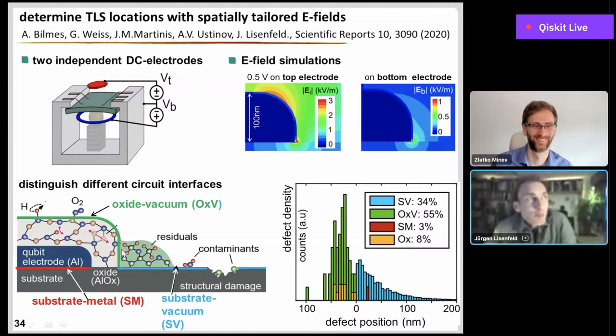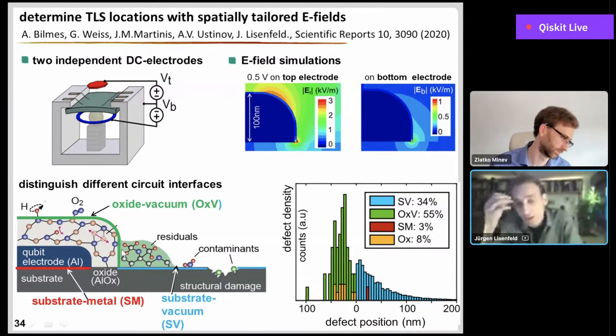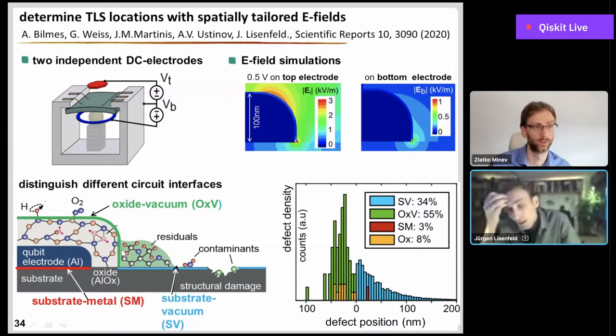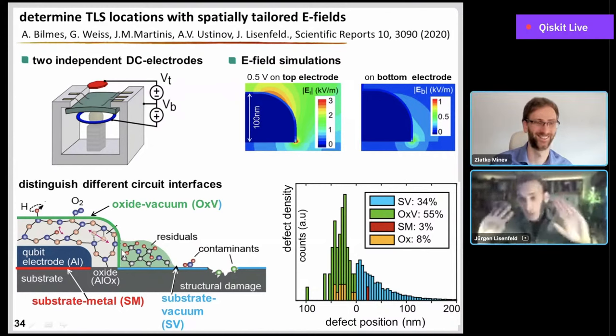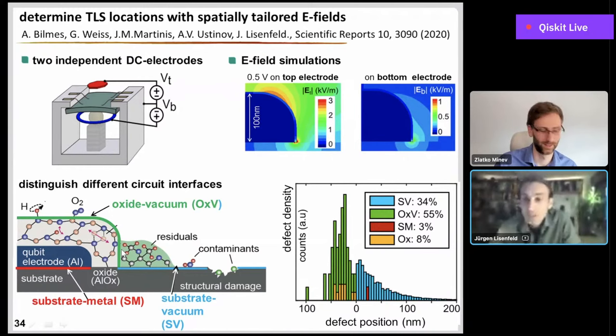In fact, I did do long-term measurements because some of the first phase qubits that I had, I was measuring for more than 10 years, but not on the level that I could detect any of these changes that you mentioned. It would be very interesting to see how this junction aging changes also the defect density in the barrier. So this could be very interesting also to learn where this aging actually comes from. So for example, to learn what is diffusing inside these tunnel barriers. We did not do this, but it would be a very interesting thing to do. And I guess we are planning such measurements also.